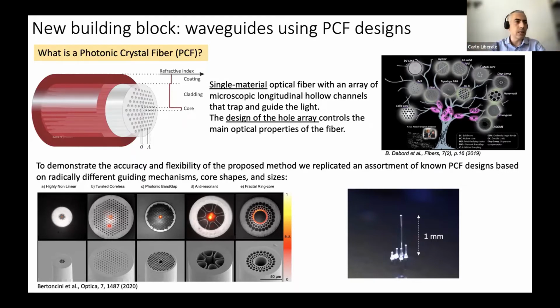And then there are other technical concerns related to the machine. But for sure, this can be improved in the future. At the moment, we are able to fabricate a segment of a length of a millimeter, probably 2-3 millimeters. So it's not a fiber of a kilometer, but this is enough for creating an optical element on the fiber end. Because what we do with this is we exploit the waveguide to change the shape of light at the output of the fiber to implement a function.